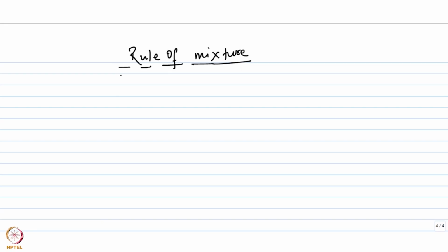Okay, so in a composite material, let's say you talk about any property such as the elastic modulus, let's say, that will be a weighted average of the elastic modulus of the matrix and the reinforcement. So if Vf is the volume fraction of the fiber, let's say you are talking about a fiber reinforced composite over here, then the elastic modulus of the composite will be given by this as per the rule of mixture.